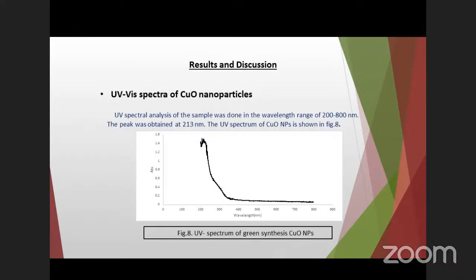Result and discussion. Our sample was characterized by two methods: UV visible spectra and XRD. First, UV visible analysis of the sample was done in a wavelength range of 200 to 800 nanometers. The maximum peak was obtained at 213 nanometers. By comparing with the bulk copper oxide UV, it is observed that the peak is shifted to the higher frequency range as the size of nanoparticles decreases.